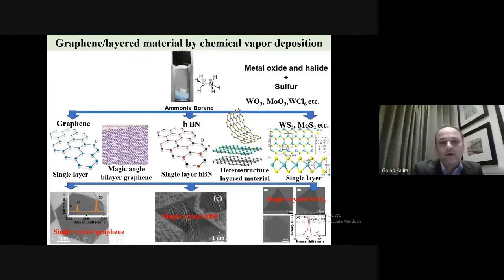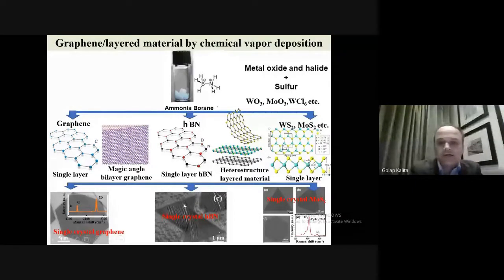Then there are lots of studies going on bilayer graphene, where when you have a magic angle in between, you can have lots of superconducting properties, and you can have this type of Moire pattern in twisted bilayer graphene. So again, hexagonal boron nitride we synthesize from ammonia borane. This is the precursor, with which we can synthesize by the CVD process, and we can get this type of triangular single crystal of hBN.